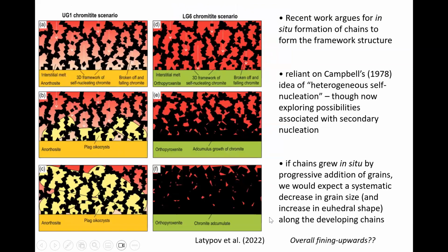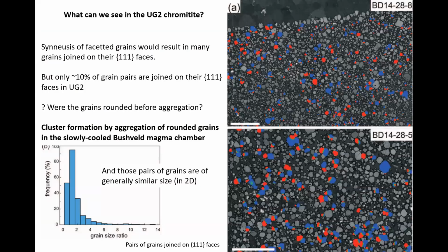Okay. So the recent work argues for this in situ formation of chains to form the framework structure. And it is reliant, although less so now, I think, on this idea of heterogeneous self-nucleation. But if the chains grew in situ by progressive addition of grains, we would expect to see some sort of progression of size, because you can't stop them growing once other grains have aggregated on top of them. So we might expect to see an overall fining upwards, but we don't.